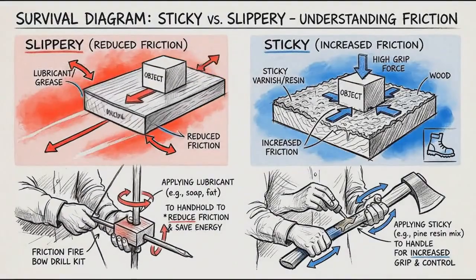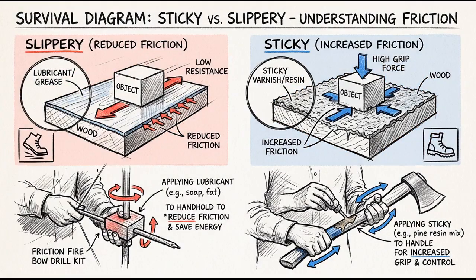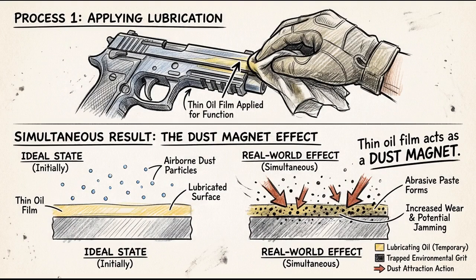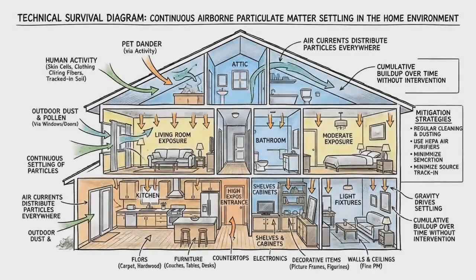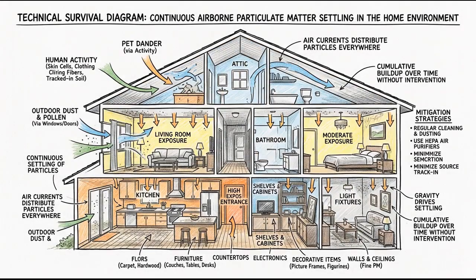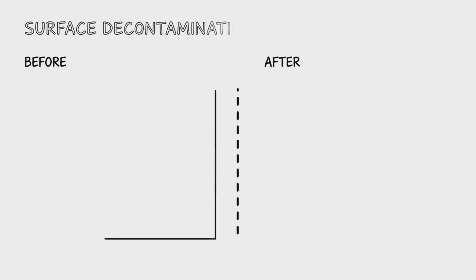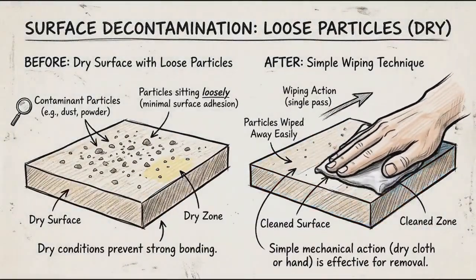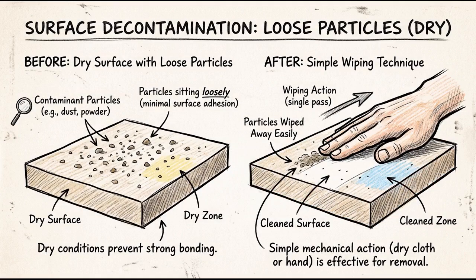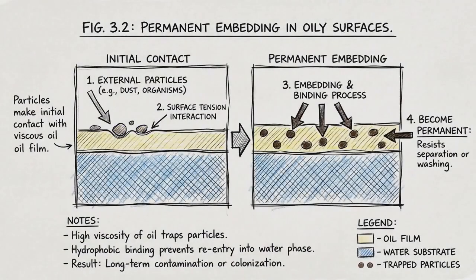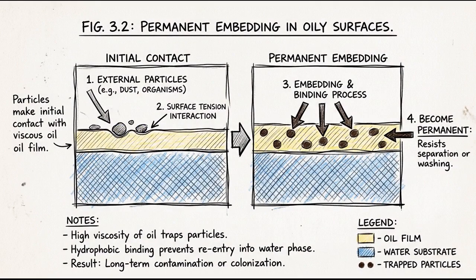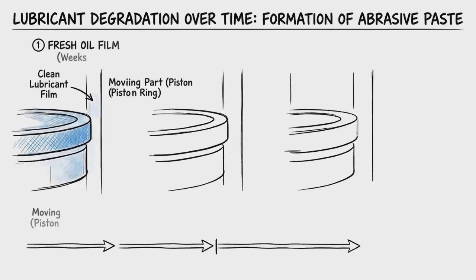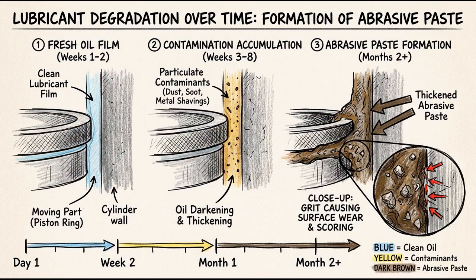Simultaneously, the thin oil film acts as a dust magnet. Every surface in a home has airborne particulate matter settling on it continuously. On a dry surface, these particles sit loosely and can be wiped away. On an oily surface, they embed into the oil film and become permanent. Over weeks and months, the oil film accumulates enough particulate contamination to form an abrasive paste. This paste accelerates mechanical wear on the hinge pin, drawer slide, or other moving surface.